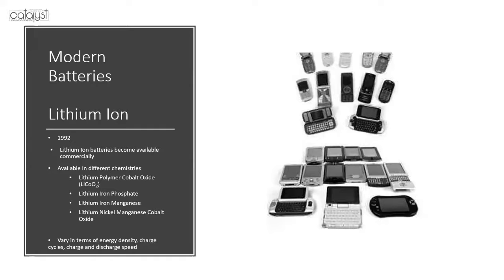And so a similar but slightly different battery chemistry, the lithium nickel manganese cobalt oxide. You see this type of battery in the LG Chem or the Tesla Powerwall, and it offers high energy density and stability, but the use of cobalt does increase the risk of thermal runaway, as we saw with that Galaxy Note example. The final battery chemistry I'll touch on is the lithium iron phosphate, which is a newer battery chemistry, which makes it a little more expensive than others, but it does have its applications, and a company called Sonnen, which I'll mention later on, uses this type of battery as a home battery storage unit. And so some of the advantages that this chemistry offers is greater safety and thermal capabilities, so it has a longer life. Since they don't generate heat, they also require very little cooling and mean they can be installed in more unique indoor applications.